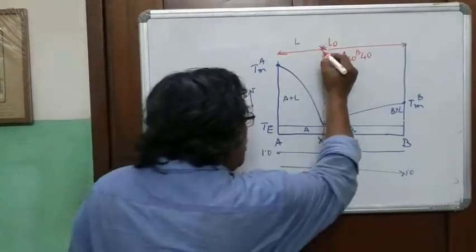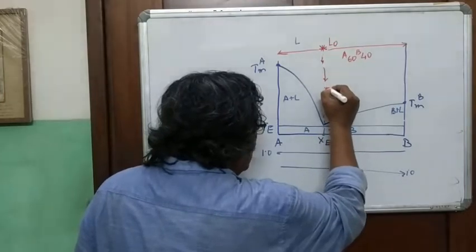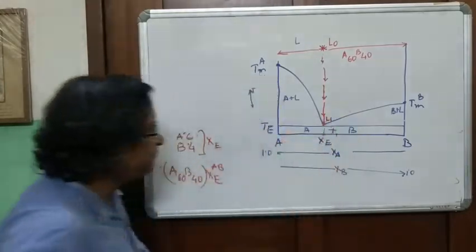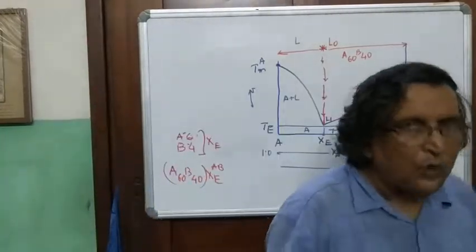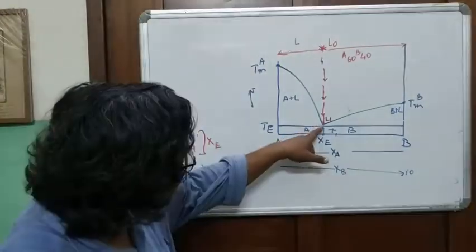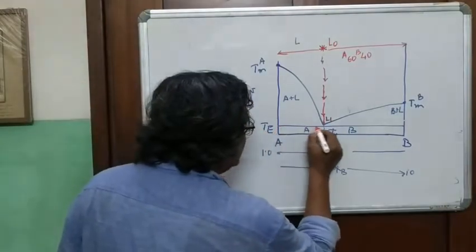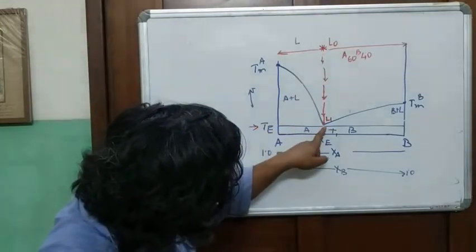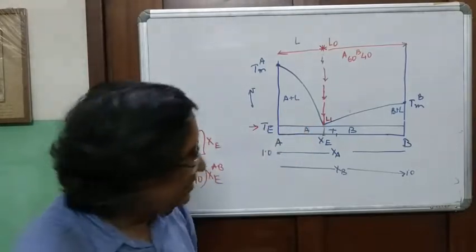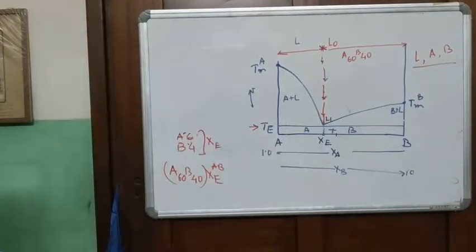Now, if you cool the liquid, the liquid coordinates move along this line till you reach the position, say L1. Now, at L1, what is the composition of the solid? What is the temperature at which crystallization starts? The temperature where the crystallization starts is the temperature of the eutectic. This is the temperature at which crystallization starts. Why? Because now the melt composition has reached this point where liquid A and B are equal. So if it is so, then A and B have to precipitate out.